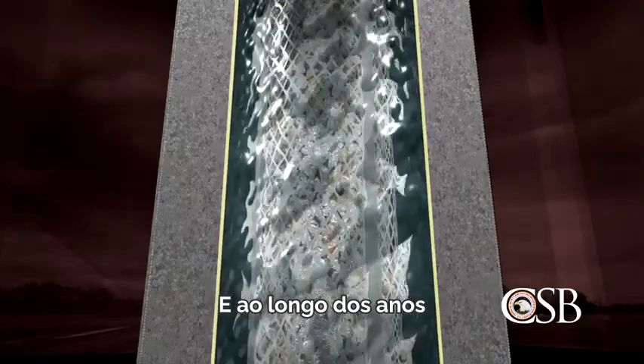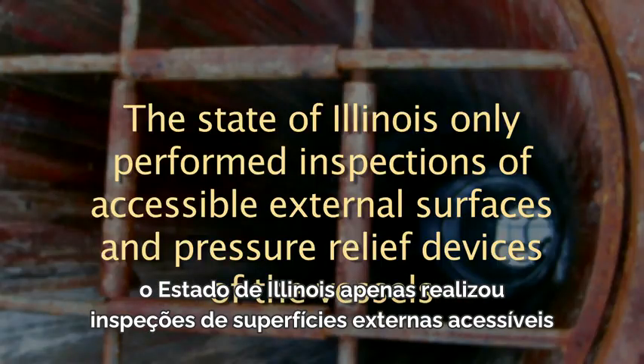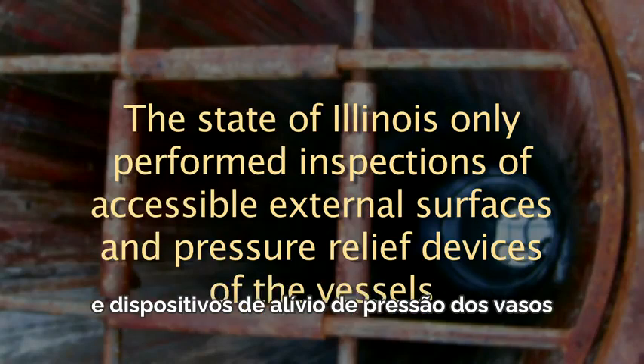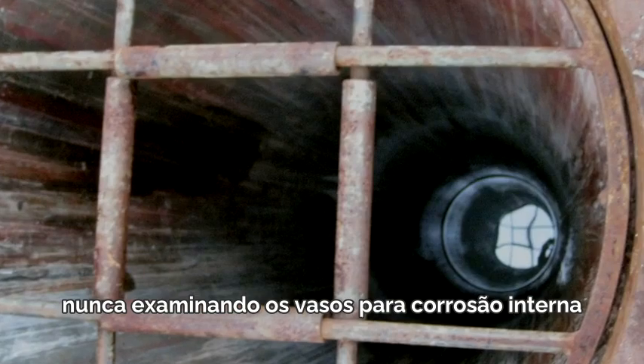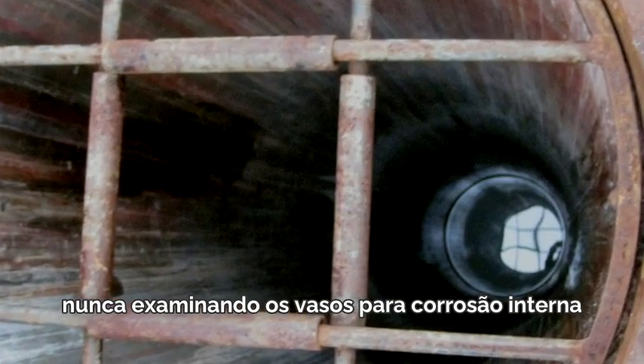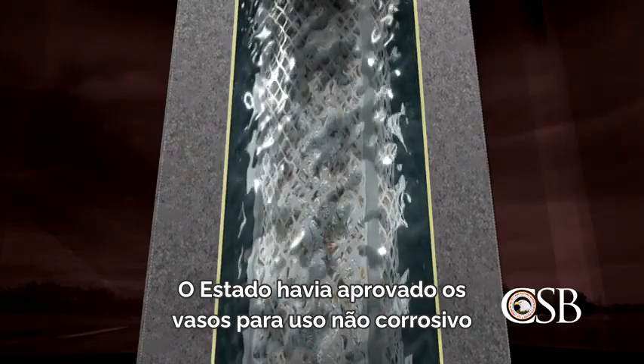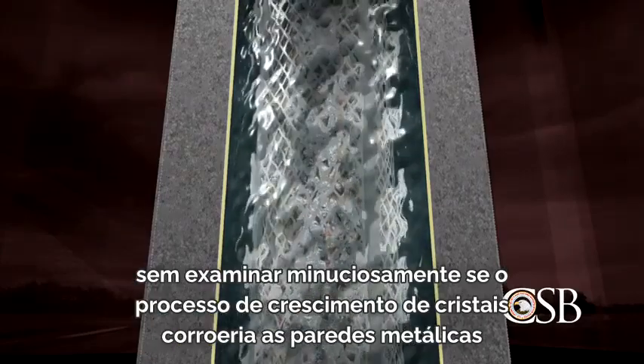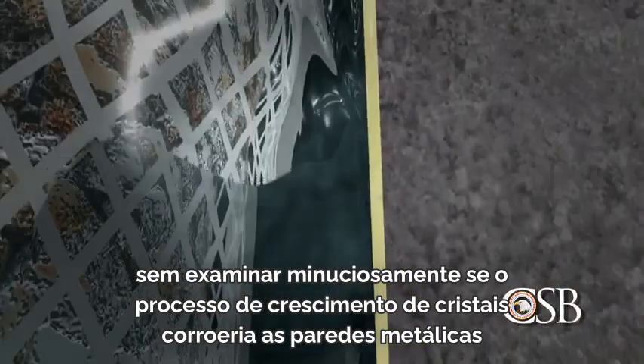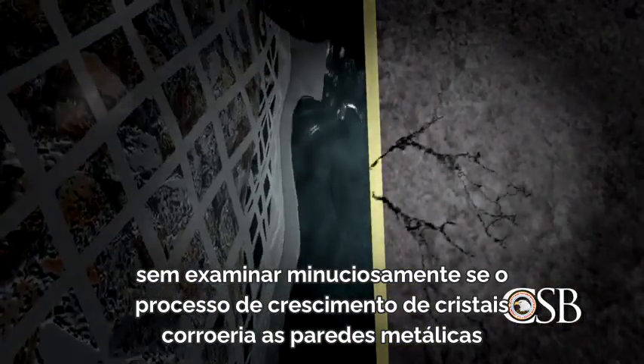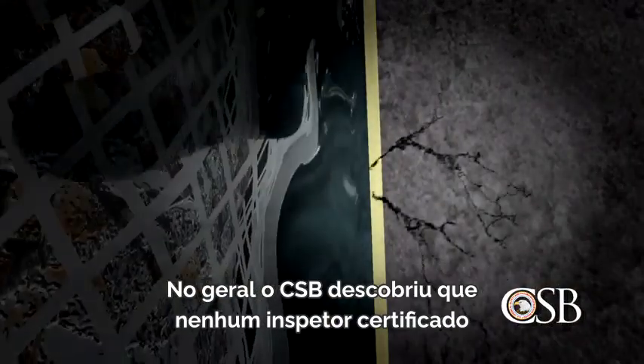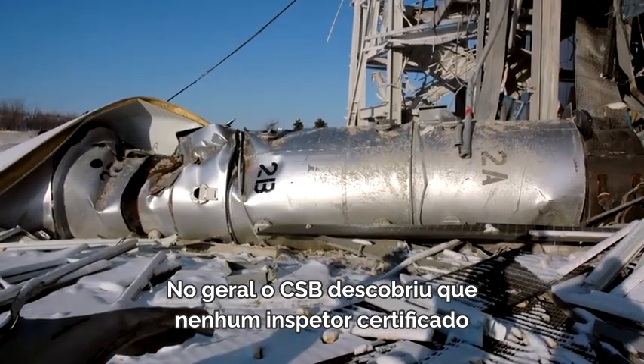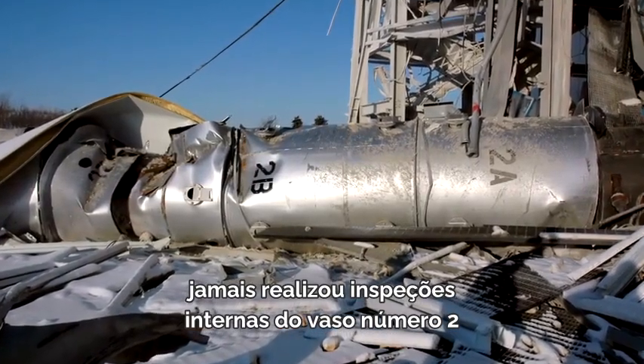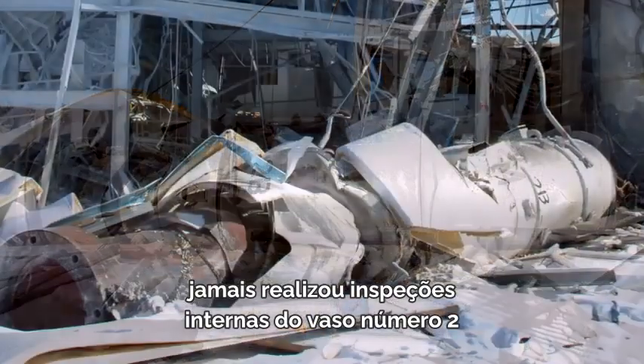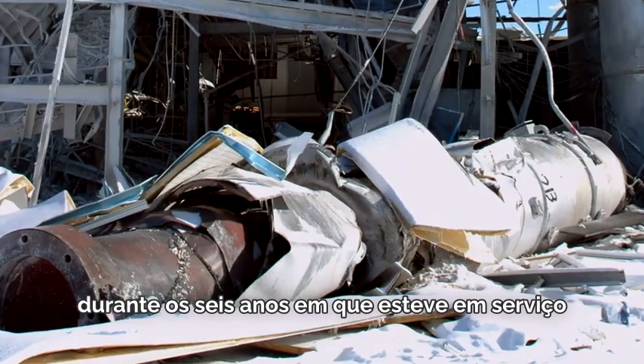And over the years, the state of Illinois only performed inspections of accessible external surfaces and pressure relief devices of the vessels, never examining the vessels for corrosion inside. The state had approved the vessels for non-corrosive use, without thoroughly examining whether the crystal growing process would corrode the metal walls. Overall, the CSB found that no certified inspector had ever performed internal inspections of vessel number 2 during the 6 years it was in service.